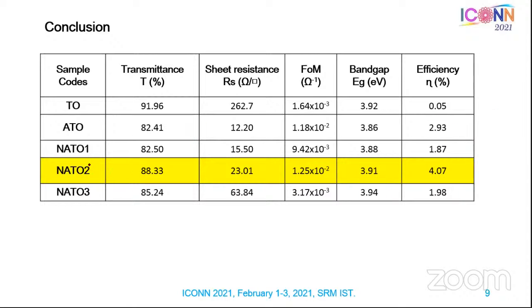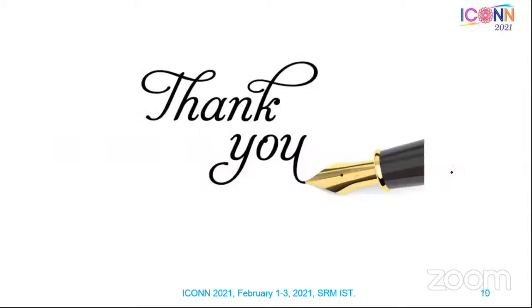But in the case of niobium co-doping, transparency is increased for NATO 2. So sheet resistance is slightly increased. The figure of merit is also increased compared to ATO and tin oxide. So it is showing an efficiency of nearly 4. Thank you, sir.